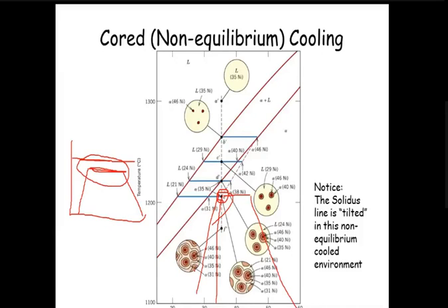So what we do is heat this alloy below the solidus temperature line for a prolonged time. We will hold it there. So what happens during this holding process? All the solid atoms redistribute themselves, and due to this redistribution, you will get uniform alpha of chemical composition 35, and that is due to the diffusion process.